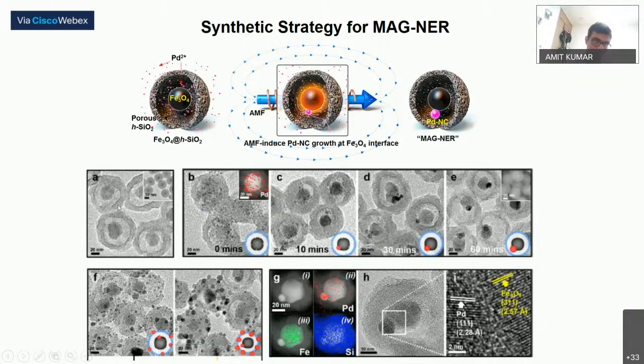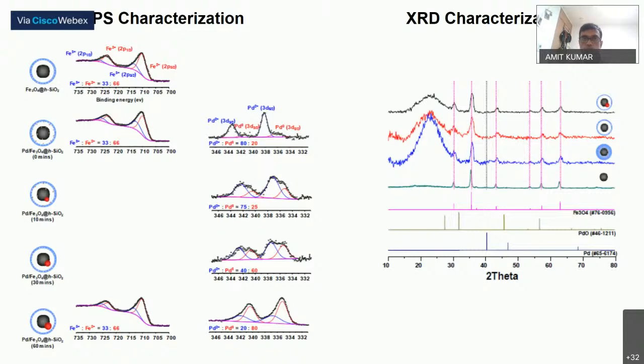So as you can see, these are the TEM images of time-dependent reaction monitoring. So the first, this is A, is hollow silica, and inside there is iron oxide nanoparticle. And after mixing with palladium precursor, we see formation of these kind of dots, which could be palladium species aggregated. Some time we see the emergence of small palladium nanocrystals, which finally convert into a single palladium nanocrystal located onto the magnetic core. And using only thermal heating could generate palladium nanocrystals non-specifically throughout on the silica surface, which was not desired. So it shows the utility of magnetic field in synthesizing such a nanostructure selectively only inside silica. And the structures were characterized by various techniques, including XPS based chemical characterizations and also XRD characterization.